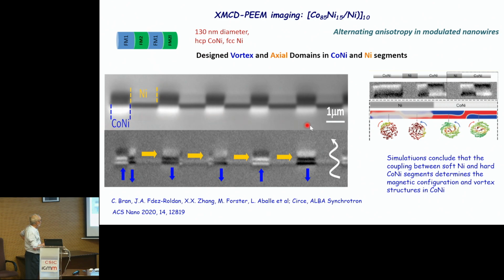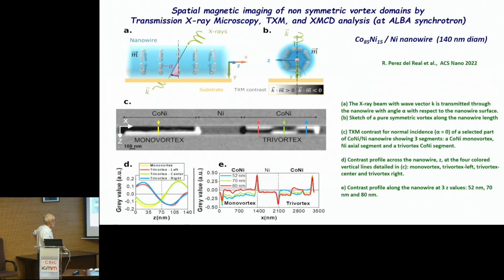You see, this is a topographic image. They are very well resolved, the cobalt nickel and the nickel segments. And this is the magnetic image obtained in the synchrotron. So in the nickel segments, magnetization is axially oriented, but in the cobalt nickel segments, we observe vortices, and this can be controlled by the length of these segments, etc. Also, there have been some simulations. I will not be talking about them now. And it's also a very recent result.